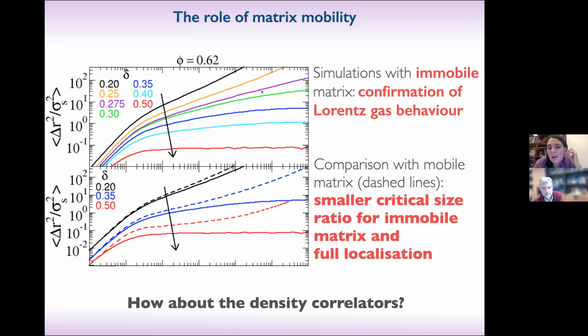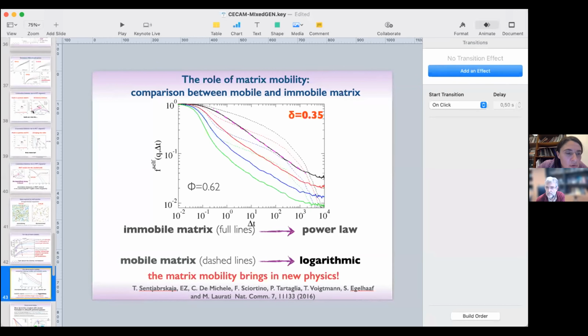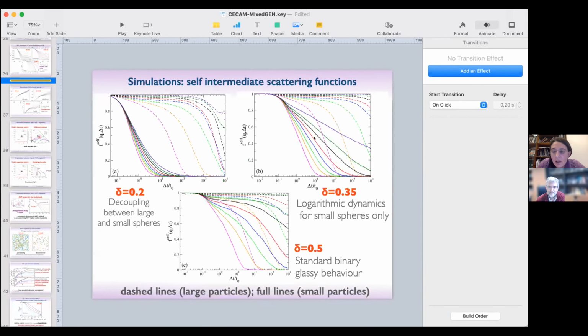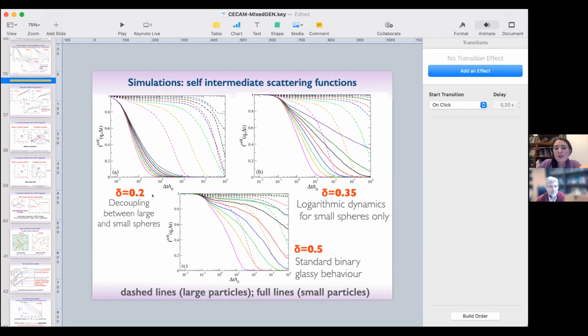Yeah, you are right. We didn't do it. We simply calculated. I'm not showing results for the large spheres, because they were glassy. I had a slide that I decided not to show because I had a lack of time. You see that I show both large and small spheres, and these are the small ones at low size ratio that are basically diffusing and relaxing very fast, and these are the large ones. As you increase the packing fraction, they become glassy. So we have not averaged, but overall, at least up to this packing fraction, they are kind of in equilibrium because they fully relax.